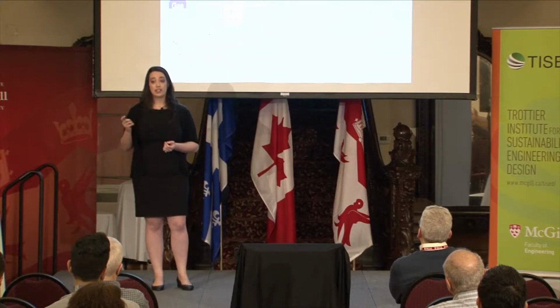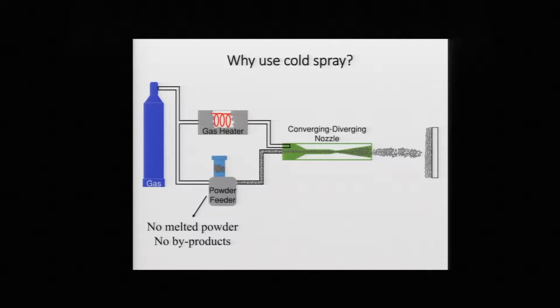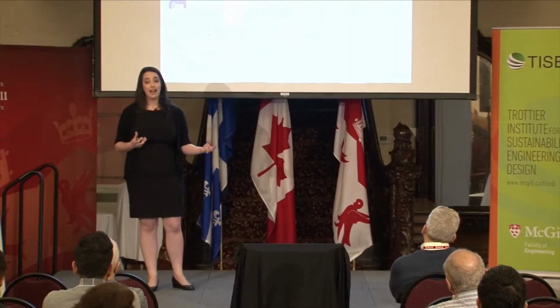But another interesting thing is that the heat input that we're putting in, so the energy that we're putting into the process, is actually not significant since we're not melting that powder. And also, there's various research being done to optimize the nozzles to try and increase velocity simply through the nozzle characteristics, rather than increasing velocity through an increase in temperature. So if we do this, we might eventually even remove the need for that heat input.